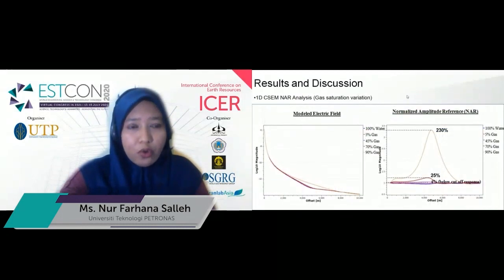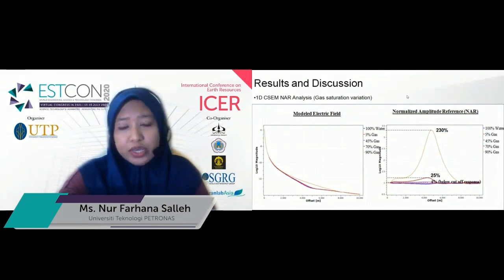This is the result of 1D CSEM for gas saturation variations. So we can see from the right figure, only 90% and 70% gas have the response more than the 15% cutoff, where 70% shows the response almost 25% increase, and 90% gas shows the response almost 230% increase.